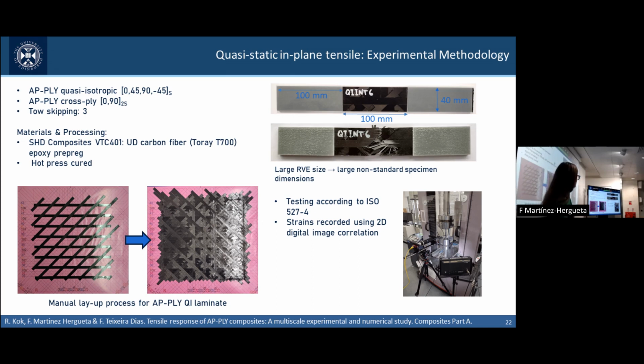So he designed two different preforms, a quasi-isotropic one with angles at 0, 45, 90, and minus 45 degrees, and a cross-ply laminate at 0 and 90 degrees. The tow skipping parameter, which just reflects the number of tows that go in between the passes, is 3. That can be defined, and in the paper we have explored what happens when you change that skipping parameter.